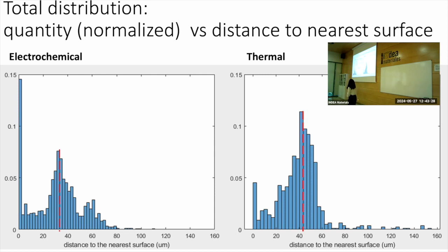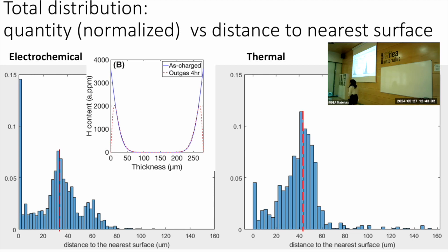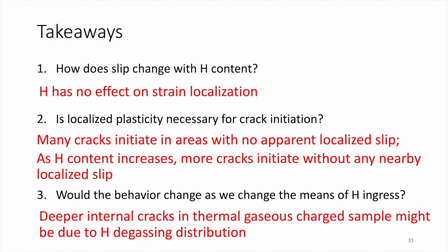If we take a look at the hydrogen distribution in the electrochemically charged one, after the 4-hour degassing, the majority of the hydrogen was sitting here, so it kind of matches between here and here. We still don't have the profile of the thermally charged one, but we are hoping to see how these two correlate with each other. So here are the takeaways. First, hydrogen has no effect on the strain localization. Second, as our hydrogen content increases, more cracks initiate without nearby local slip, and localized plasticity is not necessary for crack initiation. Third, we see deeper internal cracks in the thermal gas charged sample, and we see mostly surface cracks in the electrochemically charged sample.